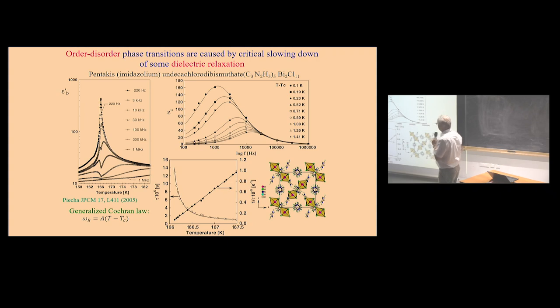In the case of displacive ferroelectrics, you have again dielectric anomaly at Tc, seen very well at low frequencies, 200 hertz, let's say. But if you go to higher frequencies, then the peak value is decreasing. It's still present at same temperature, but its value is decreasing. And then finally, at higher frequencies, you can have even minimum at Tc. Quite unusual, yeah, that you have at ferroelectric phase transition minimum at Tc.